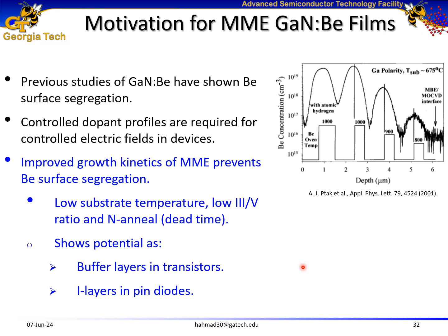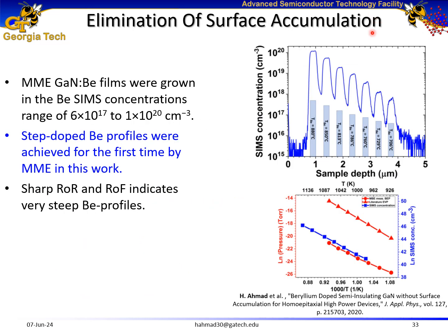Previous studies of beryllium-doped gallium nitride resulted in semi-insulating films, but they suffered from beryllium surface segregation. However, for devices, we need controlled dopant profiles to control the electric fields in devices. So my motivation for this study was to utilize the improved growth kinetics of MME to eliminate that surface accumulation issue of beryllium in gallium nitride.